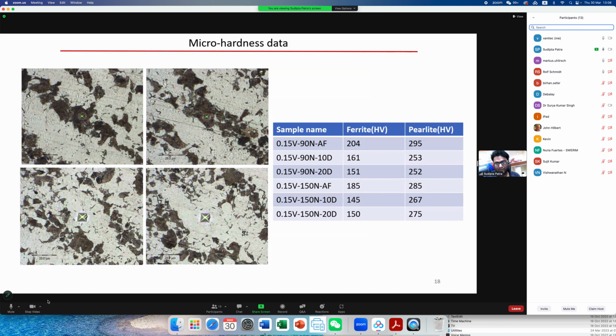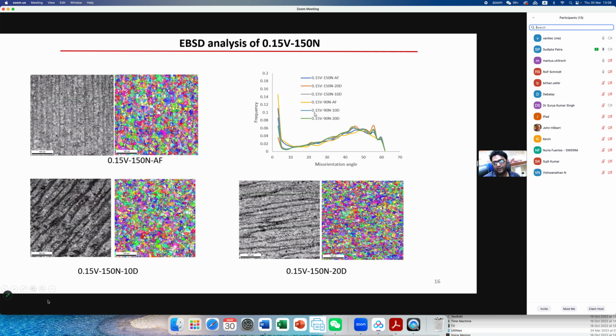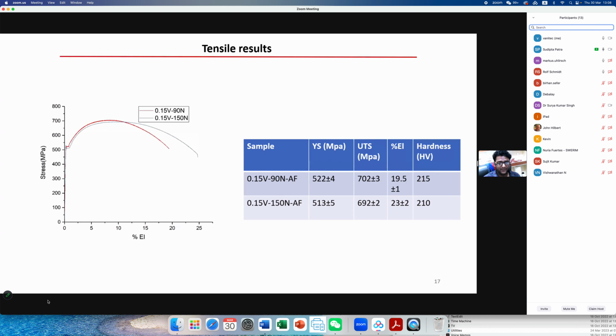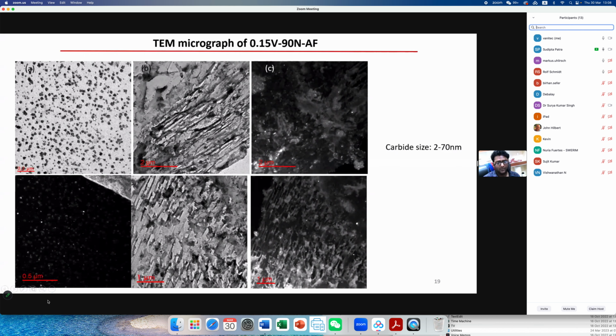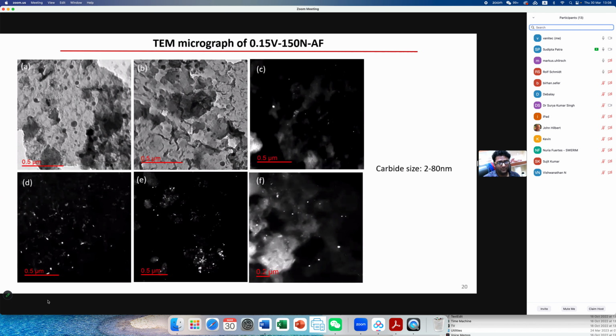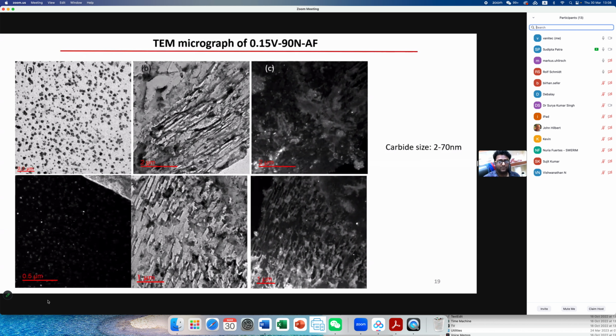So what we found is that in case of 0.15 vanadium and 90N, this as forged sample, there is a little bit of low angle boundary. Maybe the sample is rolled at a little bit lower temperature. Maybe that also contributes a little bit. But that is not very significant. The precipitation concentration is also higher. Whatever samples we have seen, there we observe a higher precipitation density in case of 0.15V and 90N, which is not expected. So I will definitely investigate in detail.